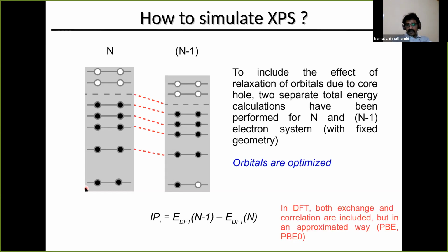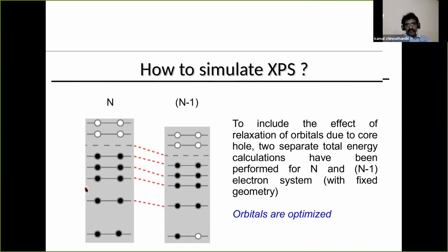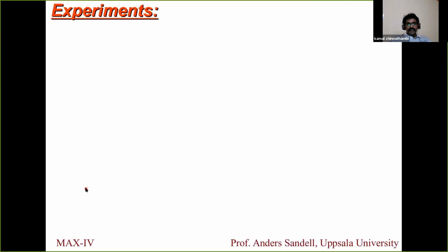But as I said previously, we missed the correlation. In DFT, by principle, exchange and correlation are both included. But everybody knows that, except for the homogeneous electron gas, we don't know the exact form, so we need to go for an approximation called the exchange-correlation functional. We use the standard GGA, that is PBE, and we also went for PBE0, which is a hybrid calculation. So this is the method we use for the calculation.